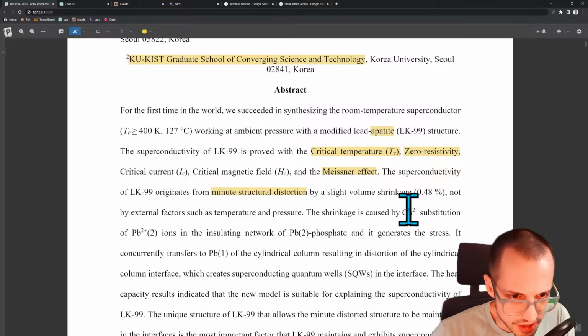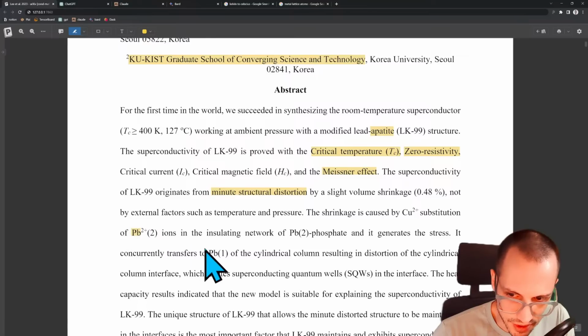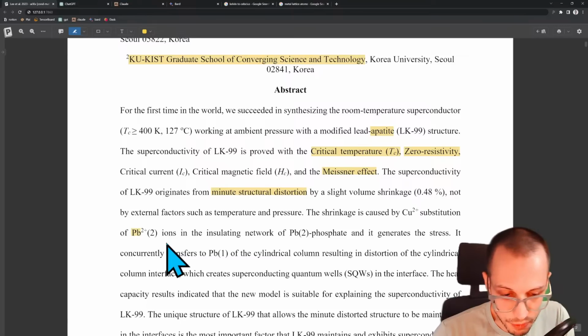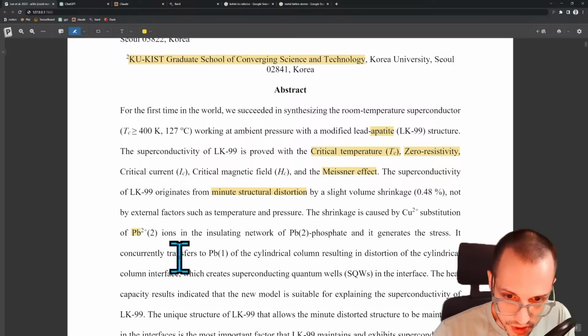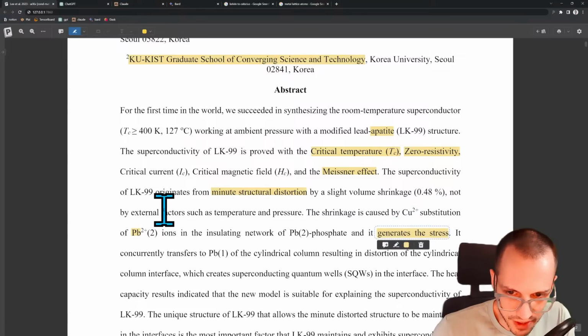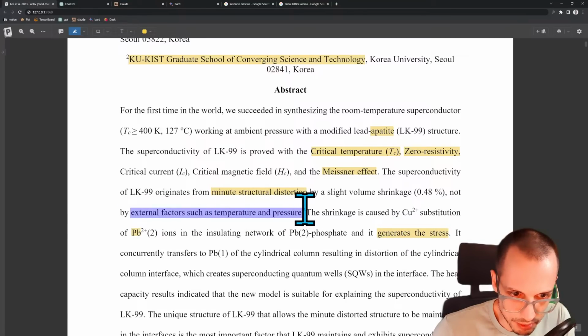So the shrinkage is caused by Cu2. Cu is copper, and then Pb is lead. Pb is the lead because in Latin, Pb stands for plomb or plomo, the Spanish and French words for lead, and that's why it's Pb, even though we call it lead with an L-E-A-D. So it seems like they substitute the copper with lead in the insulating network of the Pb2 phosphate, and it generates the stress. Okay, so it sounds like basically in order to get superconductivity, you need to have some kind of stress, and normally that stress is applied via temperature and pressure, but now they're applying it by messing with the lattice by substituting copper and lead.